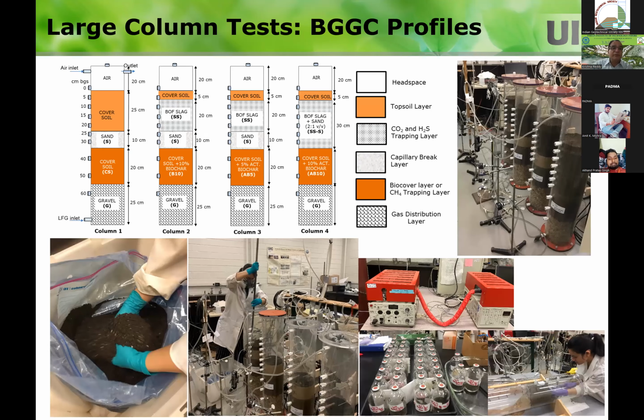So then, we put a biochar amended soil on the top of the distribution layer. Now we want to put a slag on the top of it. But that's our real hypothesis, right? We want to have a biochar amended soil, and on the top of it, we want to have a slag. And we added sand in between them just so that we can collect the sample, to see what is the gas composition that is coming from the biochar amended soil and entering into the BOF slag. So here are the pictures.